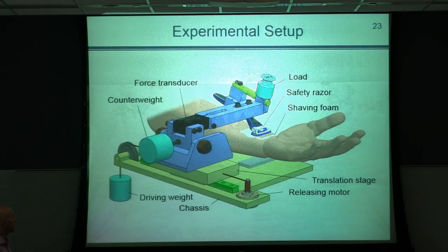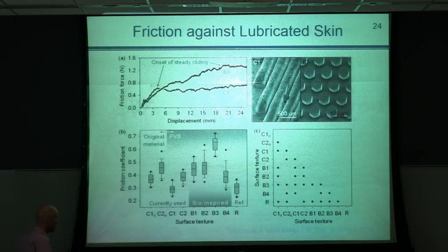So we applied a load more or less similar to the one that is applied when we shave, and the friction force was measured with a force sensor that moved with respect to the hand. And these are the results that we obtained. First of all, this is a comparison of biomimetic structure and real wipes found in safety razors that are commercially available. And this is a characteristic example of friction force measured as a function of displacement.